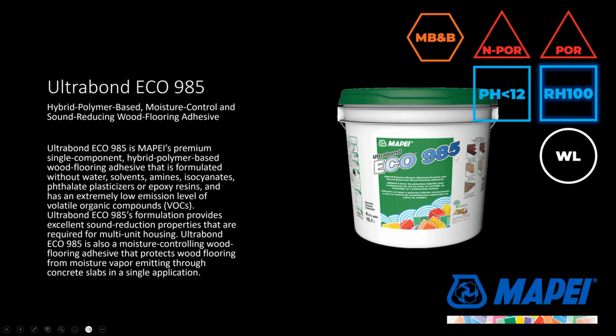Comes in a plastic bucket. It's because it reacts a little bit differently than our urethane counterparts. Eco 985 comes with moisture vapor barrier bonding solution characteristics, has acoustic redampening properties as well, and his claim to fame is, with all MS products, they're easier to get off the surface of pre-finished hardwood if you make a mess. Urethane adhesives like to grab onto urethane finishes, are very difficult to get off if they dry. MS adhesives will come off the floor and will easily rub off with a white rag on the surface without causing any etching or damaging.